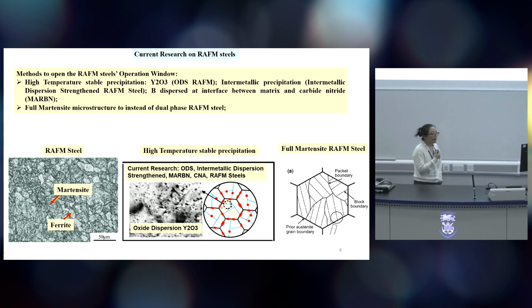two areas. One is to design high temperature stable precipitates. This can increase the steel strength, and the precipitates can also become trapping positions for the irradiation-induced defects. The second option is to produce a full martensite structure. This structure can avoid abnormal ferrite grain growth and improve the steel strength. This solves the high temperature irradiation-induced embrittlement.